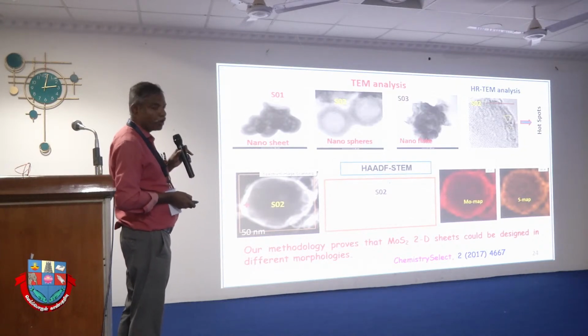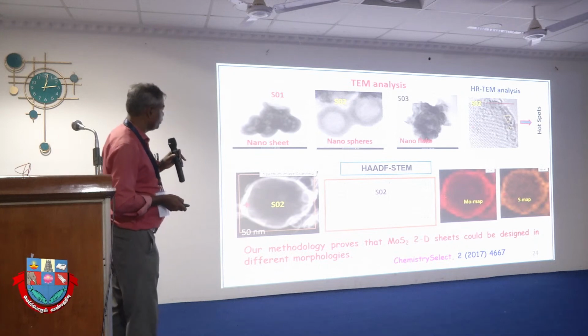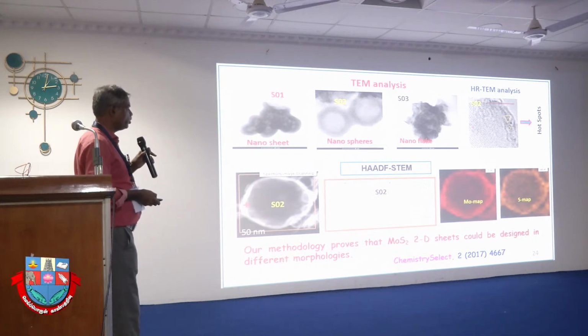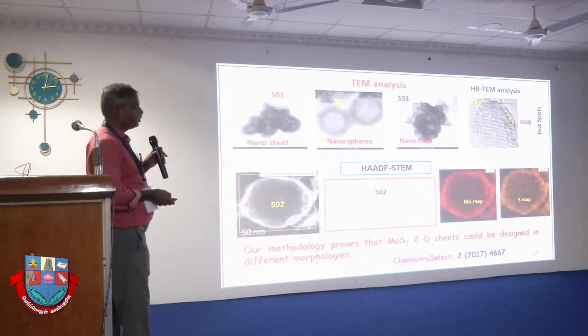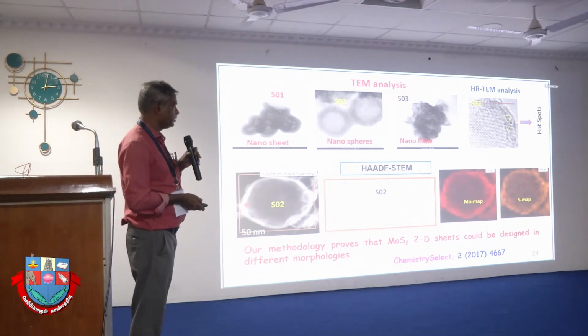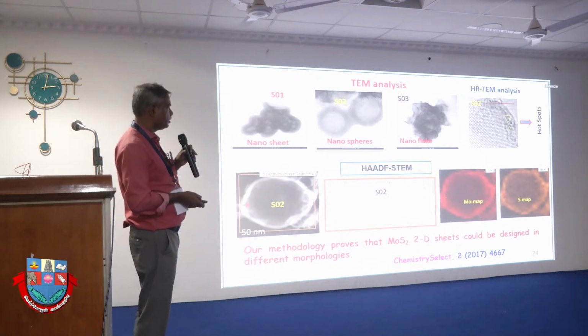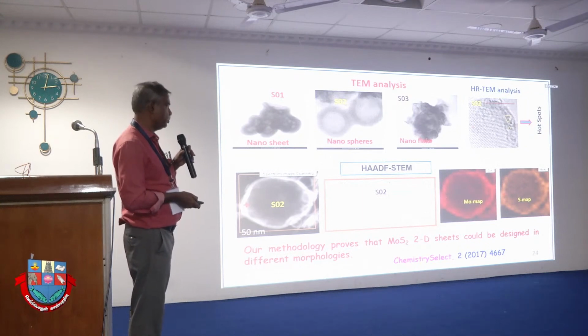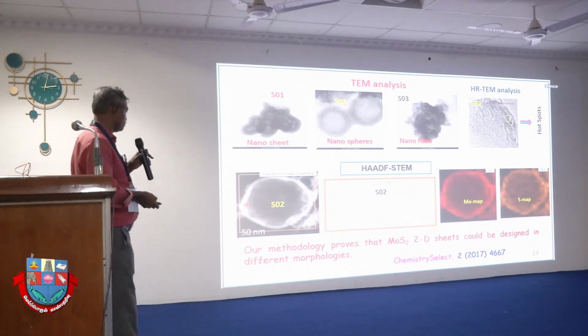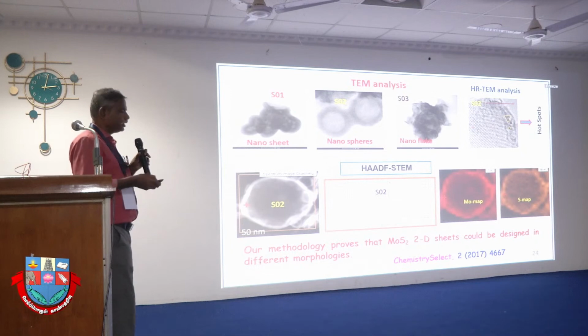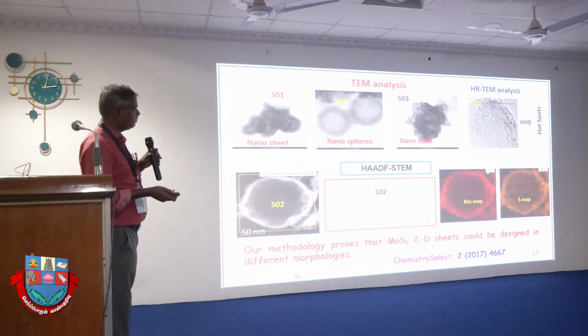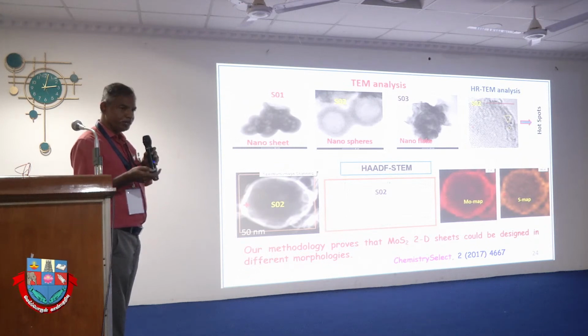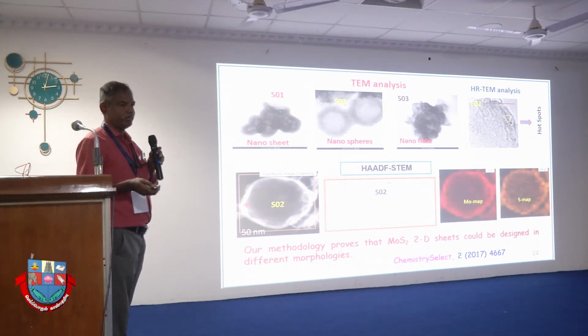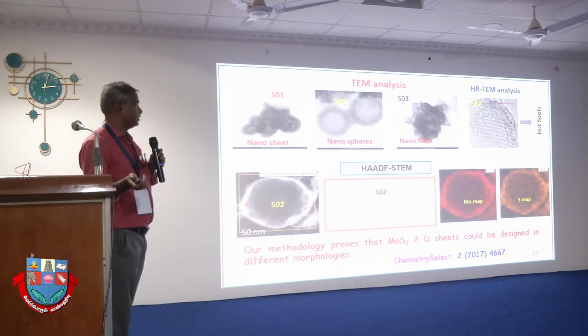They have more active sites on the edges, and then you can see that Mo and S are both distributed uniformly throughout the sphere morphology. That means the entire middle part is completely hollow, so it's almost a hollow sphere-like morphology. So our methodology proves that even though it's a layered material, we are able to alter the morphology so that we can tune the BET surface area, because the BET surface area directly affects our electrochemical surface area.